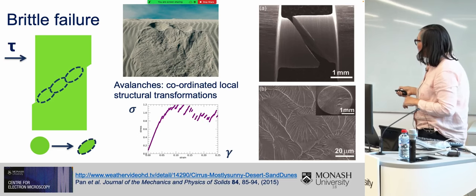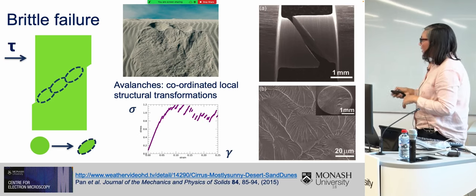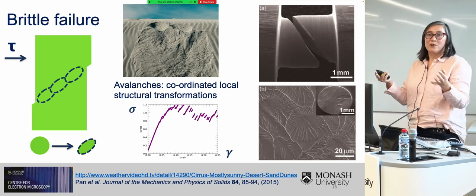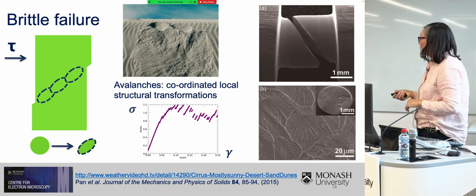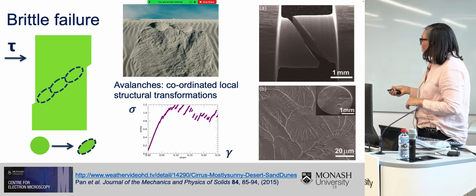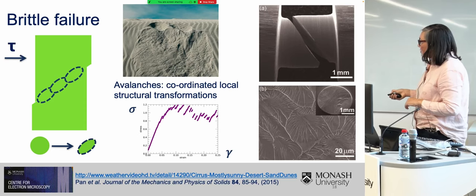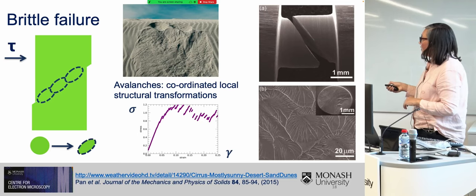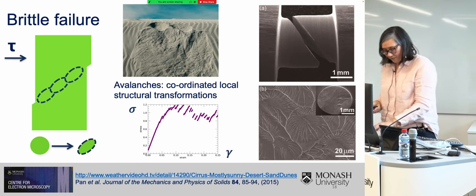So you can see small events and large events, and actually the size of the events follows a nice scaling relationship. So this is the stress strain curve from an experiment like this, where you can see that after the glass has reached its elastic limit, you have all of these different sized plastic events, and they're all of these smaller and larger avalanches in the material.